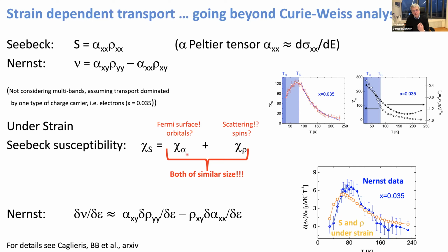So there's certainly a very strong change of the Fermi surface. It's quite natural to assume that this is really due to some orbital degrees of freedom, and that might be a starting point for, let's say, more calculations. What we did then is to take these susceptibilities, which we derived experimentally, to model the Nernst effect. We can do that along these lines, and details are described in this paper. And again, without any assumption, without any fitting parameter, you can reproduce the Nernst data from thermopower and resistivity and from their strain derivatives. That by itself is already a funny story, a very unusual thing, but it tells us that this approach, having these two kinds of susceptibilities, two kinds of strain dependence, makes a lot of sense.